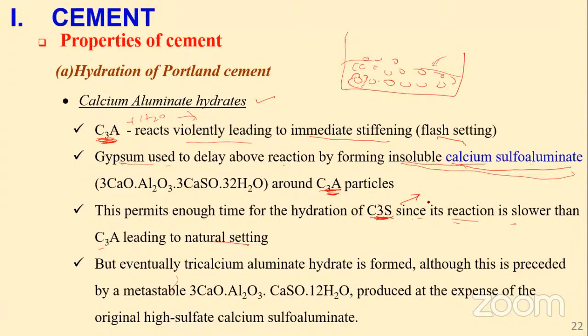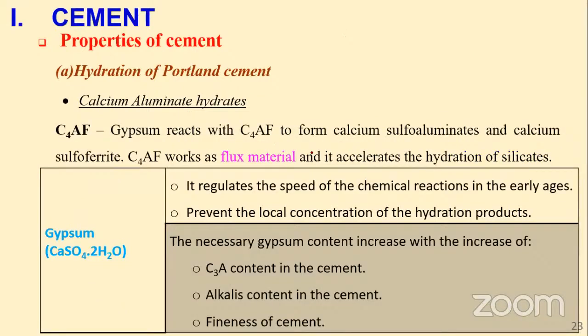But of course, eventually the tricalcium aluminate hydrate will be formed, although it will be preceded by another slightly unstable compound produced at the expense of the originally high sulfate calcium sulfoaluminate. So don't be so confused about all this chemistry. For your understanding, the purpose is to know that we have delayed the hydration of tricalcium aluminate so that we can give time for tricalcium silicate to react slowly, and also to avoid flash setting.